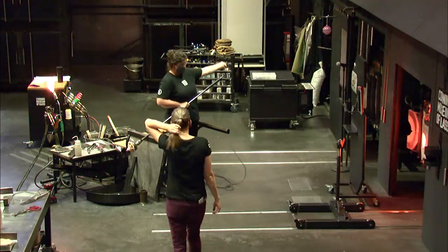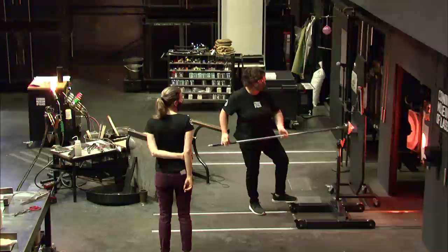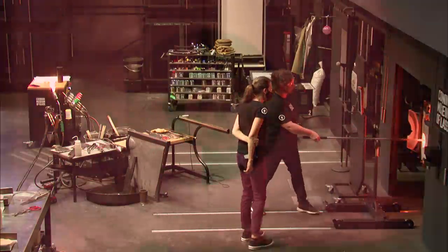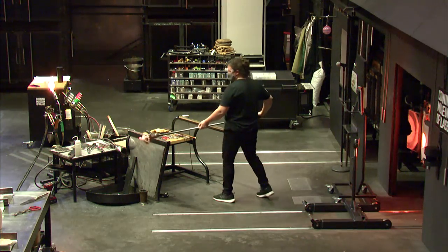That's one of the things we've kind of taken from the flame working community. Glass making over a torch, typically with borosilicate glass. It's another type of glass. You probably are familiar with borosilicate by its brand name of Pyrex. It's a glass that has a lower coefficient of thermal expansion. You can put it in your oven and it won't blow up. This glass, if you put it in the oven, can break. But that torch is used for a lot of that flame working process.